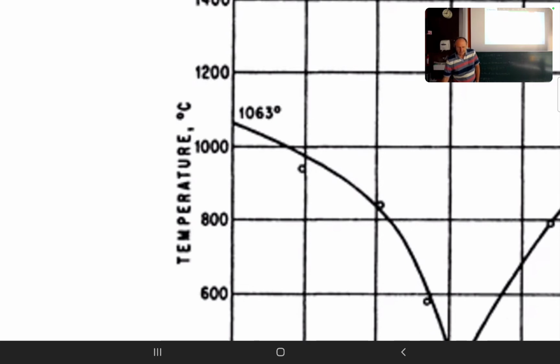So that's joy for every metallurgist. What is it here? What we see here? Yes, it's a eutectic, and that means gold melts at 1063, silicon melts at 1404, and we put it in contact and heat it, let's say without oxidizing the silicon. Then the melting point is only 370 degrees centigrade.